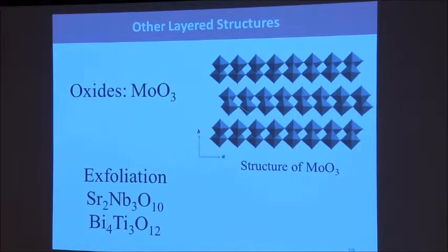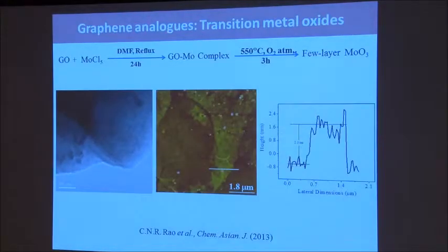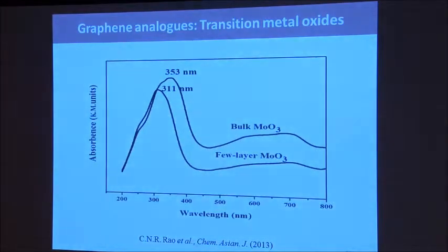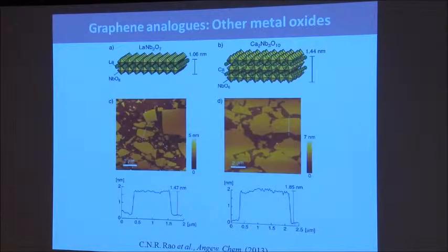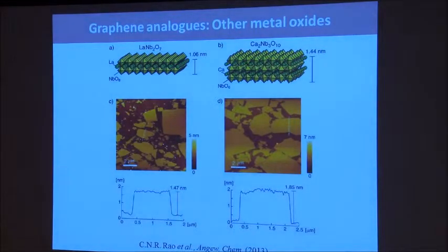For example, this oxide, very well-known oxide. So MoO3 is a layered oxide. Can I remove one layer out? Well, we have done that. We are able to remove one layer out. Not only that, we have studied, look at the electronic spectrum. The single layer MoO3 has a nice blue shift compared to bulk MoO3. We have studied a number of properties of these materials. These are all very complex oxides. You see, I can take one layer off, and see the thickness of this is all one layer or two layers, and we can study materials of this kind.